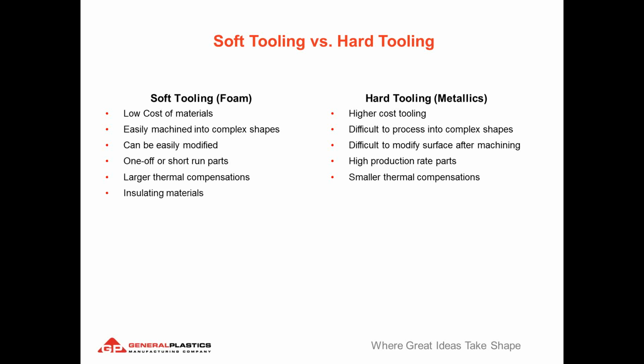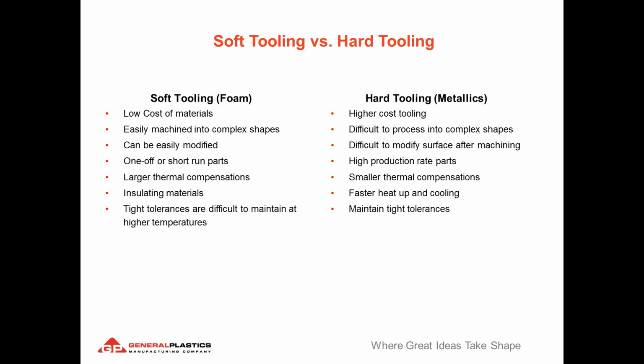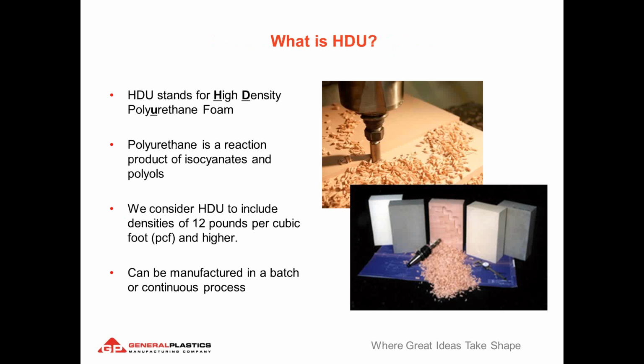Insulating materials. So looking at soft tools, you lay a composite up on top of a soft tool or foam tool. You're really only heating it from the oven exposed side of that composite. Whereas with a metallic tool and the thermal conductivity difference, you really do see heating and curing of your composite from both sides. Therefore, you have shorter cycle times. Tight tolerances are difficult to maintain at higher temperatures. That's really due to the thermal expansion coefficients of foam versus metallics. Like I mentioned, alloys like Invar, you can maintain tight tolerances through large temperature ranges. Now, what is HDU?